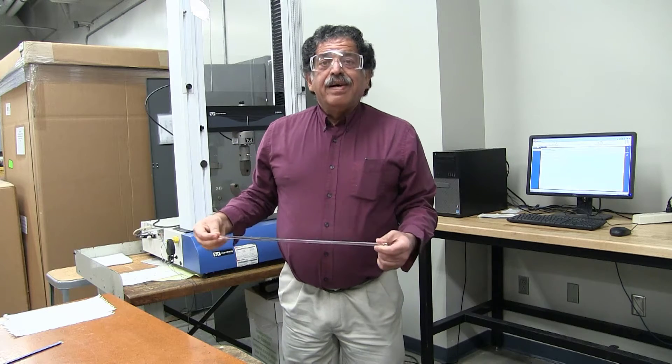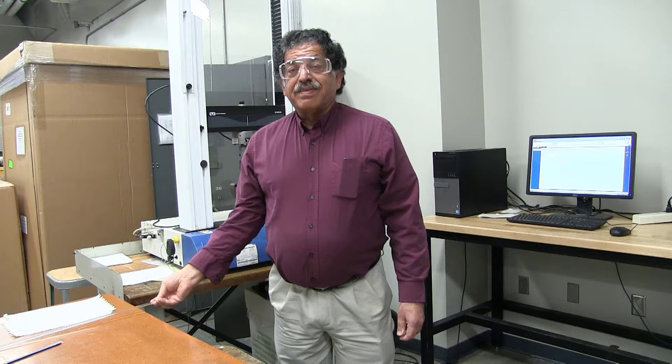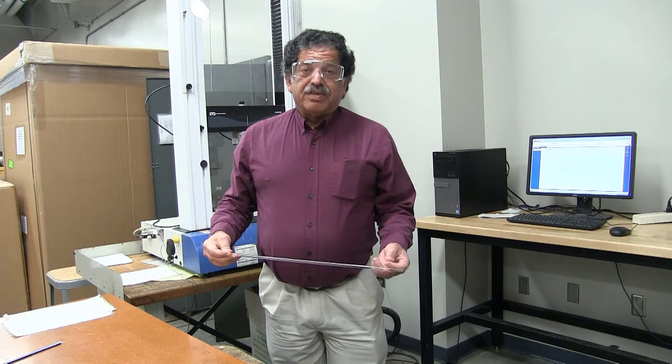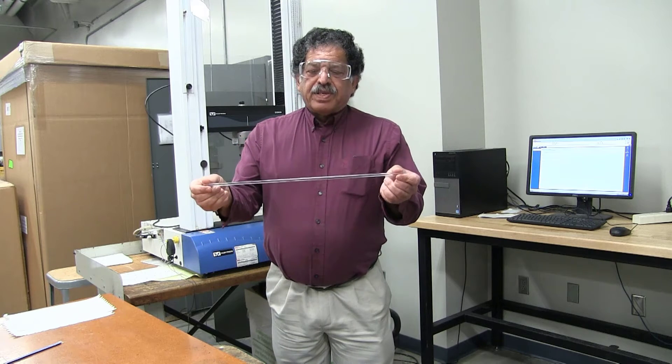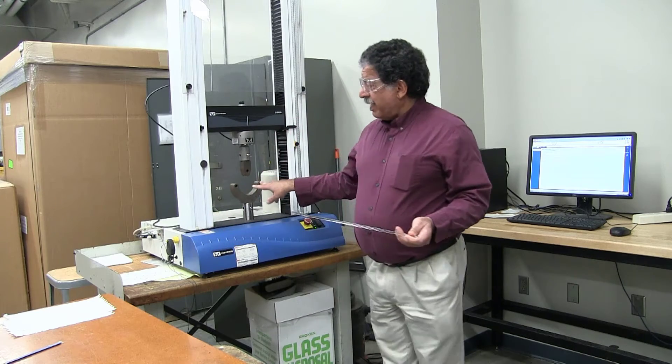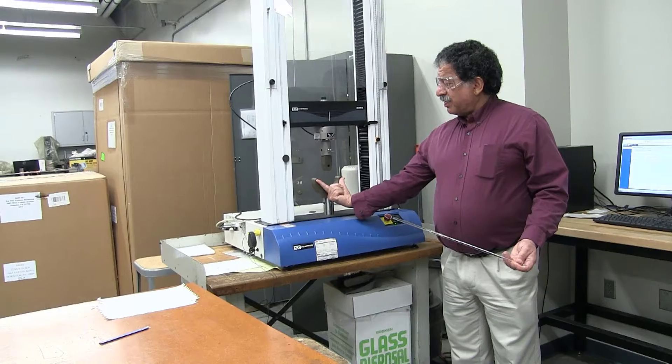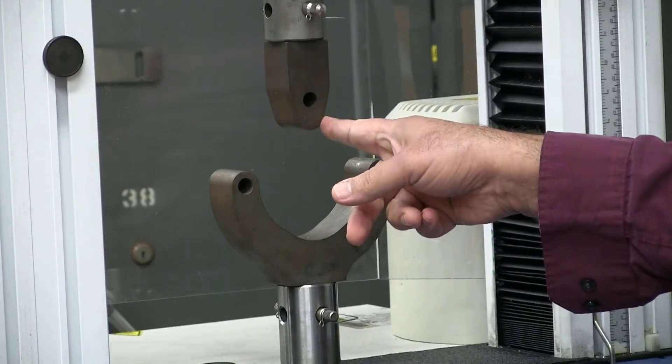There's tiny little surface defects, and if you remember from our 3150 class, the fracture of brittle materials is governed by the defects that they have, and so in this case, since this rod is going to be in three-point bending, which we're going to do on this apparatus over here, there's two supports over here, which are five inches apart, and then there's a central loading point that's going to be coming down on it.